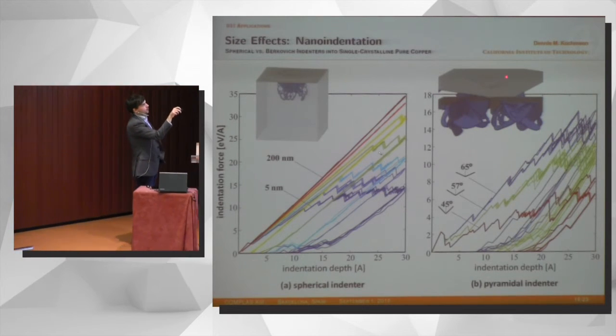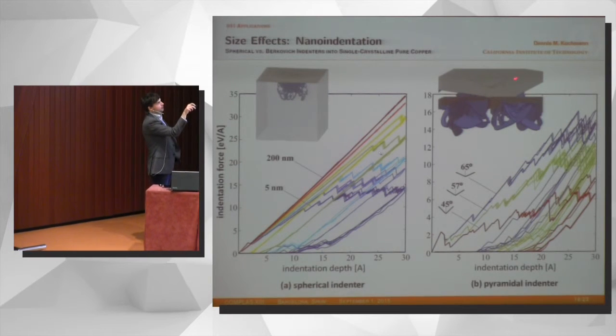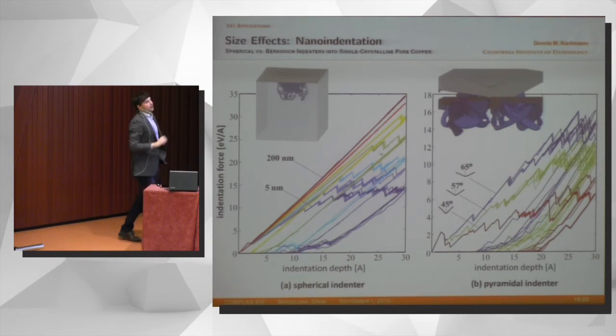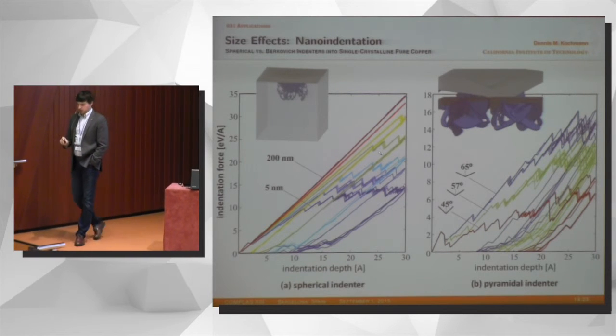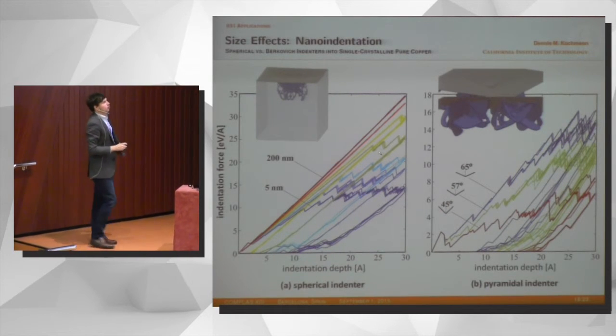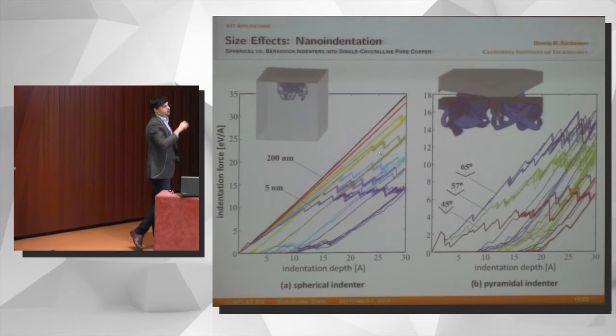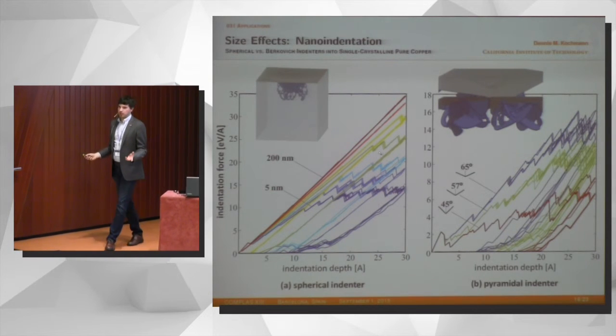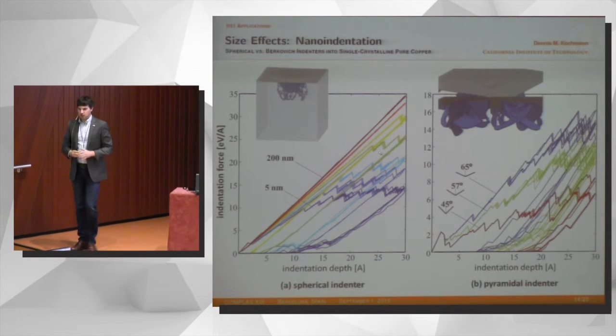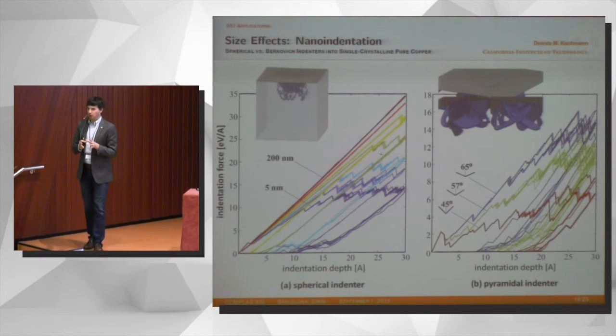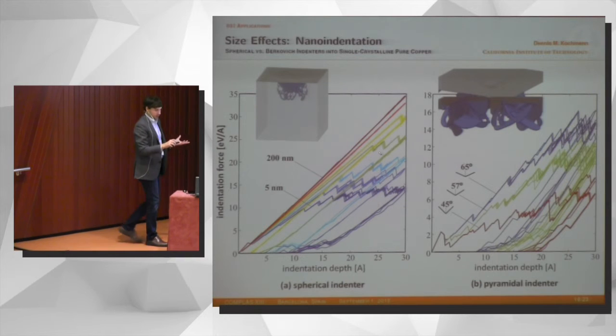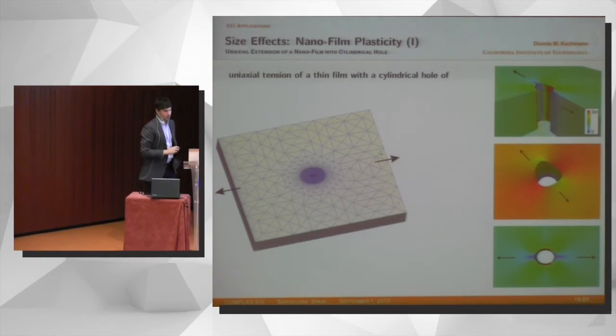Because this shape is self-similar, there is no size effect. But for example, if you vary the angle, the geometry, you can see very well the impact, and this agrees well with what's generally seen experimentally. And again, we can go to much bigger scales. A few hundreds of nanometers is easily possible, and unfortunately we're not at UT Austin. Our computer is much, much smaller, and we can still run this overnight because of the increased efficiency.